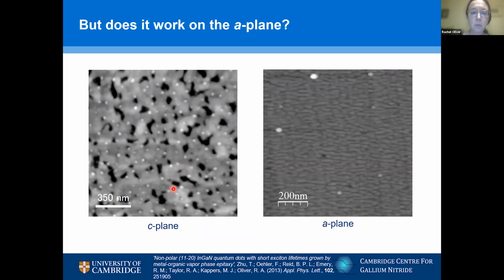And we can see that what we have is this kind of distribution of these tiny metallic droplets and also an indium gallium nitride film with holes in it. So we have a sort of quantum well layer with holes in, and on top of that, these little metallic nanostructures, which we're going to react with nitrogen to give our quantum dots.